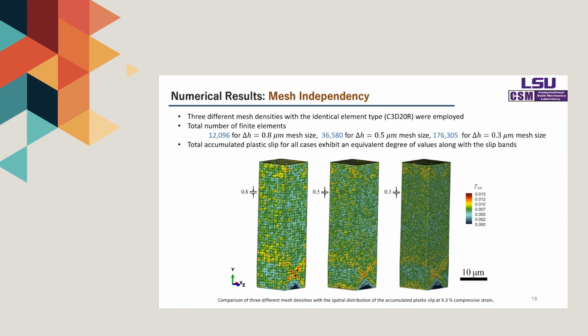The spatial distributions of total accumulated slip for all cases exhibit an equivalent degree of values along with the slip bands at the top and bottom regions of the micropillar compression. Considering the degree of difference in 3 different cases, the simulation results demonstrate the independence of the mesh density.